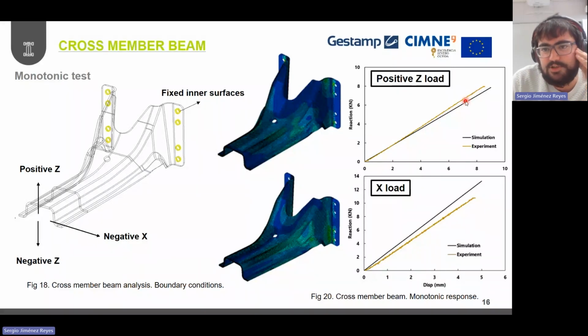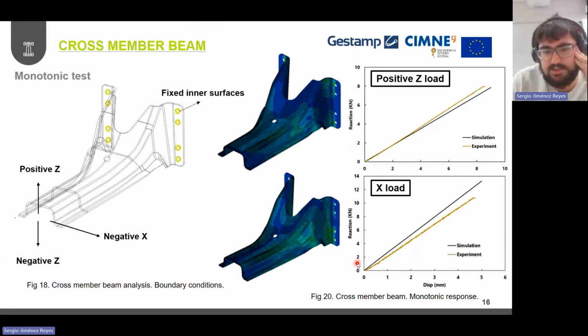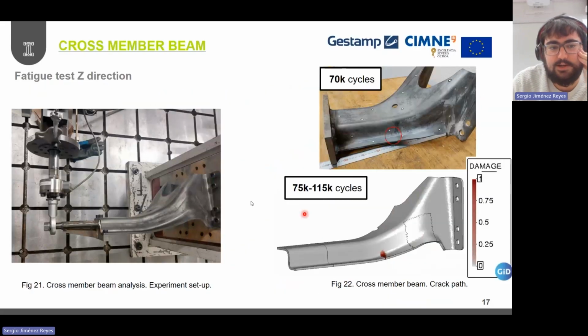A better agreement is observed for the positive Z results, but you can notice here that there is some spurious initial degradation, a reduction in the stiffness in the material, that may be the explanation for some higher differences in this monotonic response for the cross-member beam. And then finally, when moving towards the fatigue scenario, in this particular case, because we've done others, but I'm just presenting this scenario where we are applying this cyclic load in the Z direction for the cross member beam.